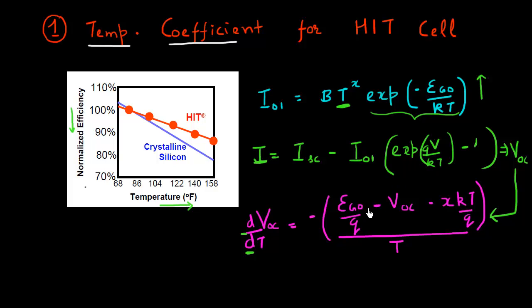If you do that, you'll get this formula where this temperature coefficient of VOC - as you see, it has a negative temperature dependence. Usually when you increase your temperature, your VOC decreases. And this is the primary driver of your efficiency decreasing as a function of temperature.